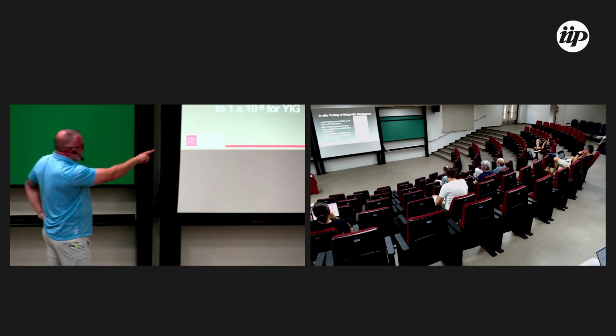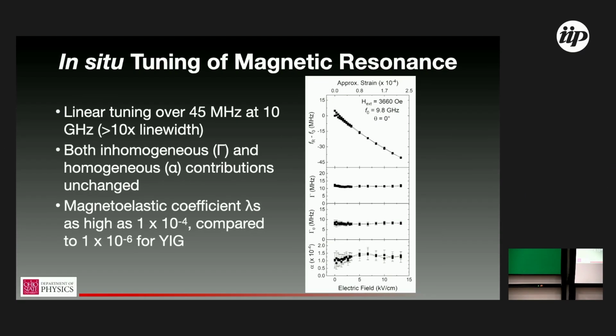And again, the numbers in the paper, I apologize for not remembering it, but one way to think about it is, the field scale that we explore here is basically most of the full functional range of what you can do with PMN-PT. So you can't strain it much more than this. We took it effectively out to the rail. So if you're used to working with the system, one could probably turn that into a ballpark for the total strain that we're introducing. But one thing to note, and that's kind of fun, is you can compare that frequency shift